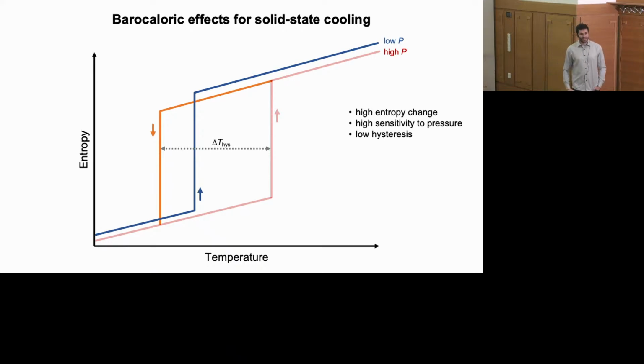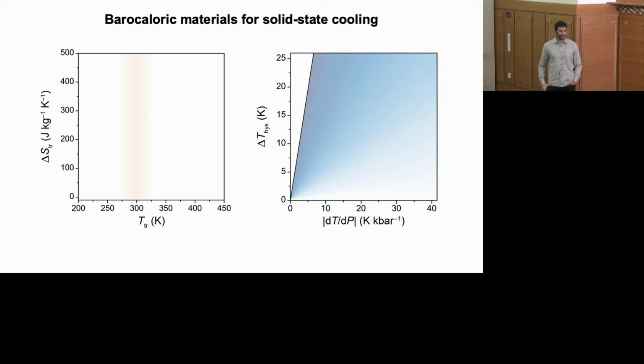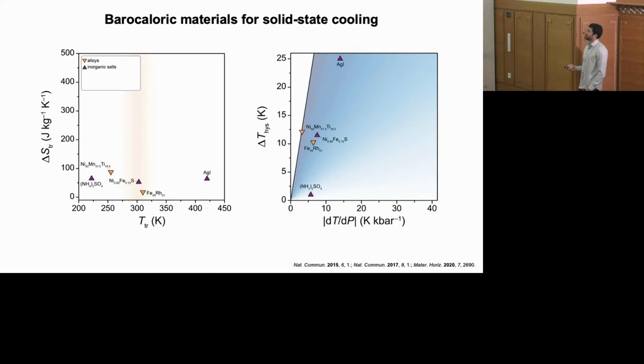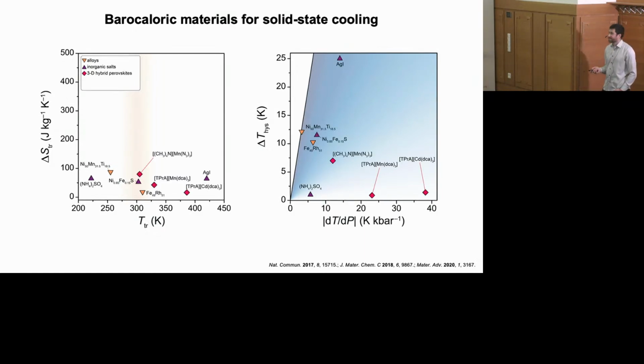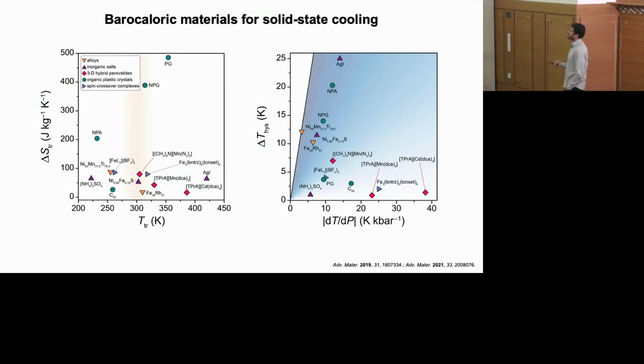But for a refrigeration system, you ideally want to drive a cooling cycle reversibly by applying as little pressure as possible. And so having low hysteresis is very important. Over the last 10 years, there's been a lot of interest in looking at different classes of both inorganic and organic materials and evaluating their potential for barocaloric effects for solid state cooling. However, it's been very challenging to find materials that undergo phase transitions that feature both high entropy changes and low thermal hysteresis and high sensitivity to pressure at or below ambient temperature. There are just not that many materials that exist in this regime.